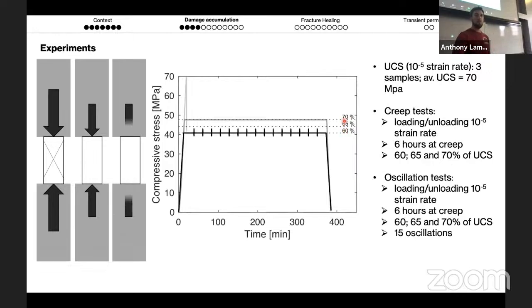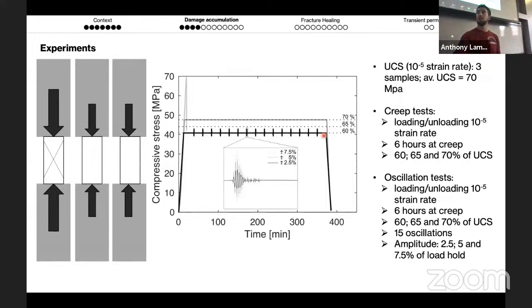And then the third type of test we did was inducing mechanical oscillations during the creep phase. There were 15 oscillations spaced by 26 minutes between each of them. We also varied the amplitude of the oscillation: 2.5, 5, and 7.5% of the load hold position. That was done for all creep conditions and all amplitudes. In the next few slides, the different shades of blue are going to show the creep condition. Light blue is the lower creep condition, and dark blue is the higher creep condition. And the size of the stars is going to show the size of the amplitude of the elastic waves.